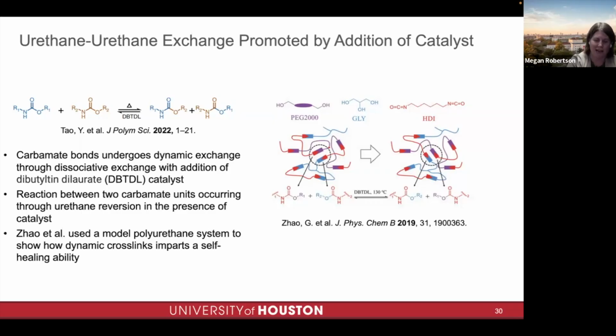So the approach we found that actually worked even better, and that enabled this entire study, is to rely on the literature on urethane exchange catalysts for polyurethanes. And this is an example. This tin catalyst, dibutyl tin dilaurate, is one that's very commonly studied. Essentially, these urethane bonds swap in the presence of this catalyst. So if the chains can swap bonds, that means you can break the crosslinks and reform them.